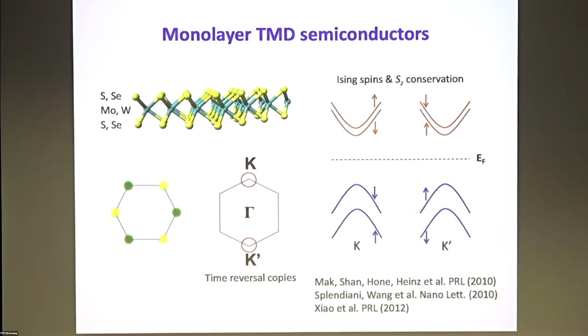Another thing different from graphene is that there is a transition metal with pretty heavy mass. And as a result, there is pretty strong spin-orbit interaction. But the spin-orbit field can only point to the out-of-plane direction because of the mirror symmetry in each of these monolayers here. And as a result, we say the spin is locked to the out-of-plane direction, and it has S_z conservation, which turns out to be important later on.